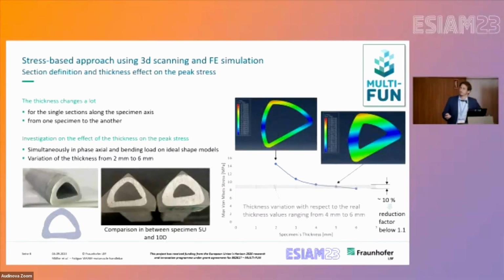So we see here, for example, two sections of two different specimens, and we can clearly see that there is no constant thickness from such a process, as it is set up right now, at least. So there are thickness variations, which we have to include in our evaluation. And it's not just differing between specimens, but also within one specimen. And therefore, there was a small pre-study focusing on the thickness of such a structure.